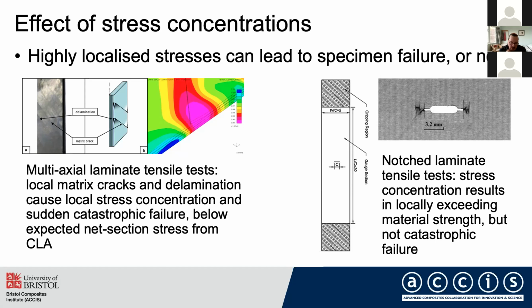reach a level above that of the very localized material failure. So as we move up the level of complexity, the failure of a specimen becomes very dependent on the local conditions prevailing, the local geometries, and the interplay between the different damage mechanisms.